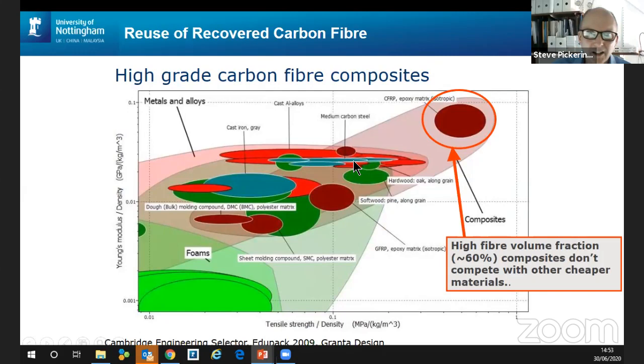Metals, aluminium, and steel are shown around here. Some of the glass reinforced composites are down here, but carbon fiber composites are up here on the top right, and they're well away from other materials. And you can achieve these sorts of properties, these specific strength and stiffness, by using a very high fiber volume fraction, 60%. And when you're using carbon fiber at these volume fractions, then the carbon fiber materials don't compete with any others, and you're really getting the most value out of the material.